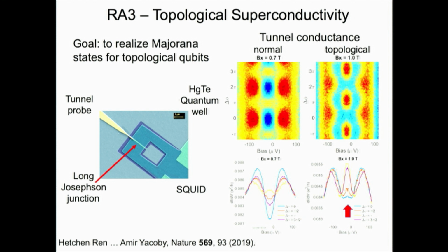And so if you inverted the conduction and valence bands, if you like, in a regular material, that's the way you make it topological. And when that happens, then you get the magic situation that you'll have a long channel where you can put an electron in the middle, and the electron is actually a superposition of two Majoranas, say a plus and a minus, or an A and a B. You can separate them and put them on the opposite ends of the wire, and they're part of the same particle, coming from a single electron that's an overlap of these two. And so they're topologically connected, but they don't have to be in the same place.